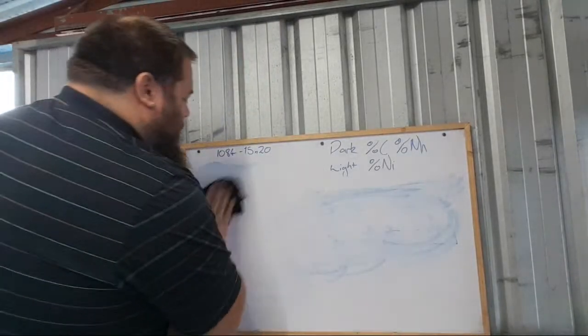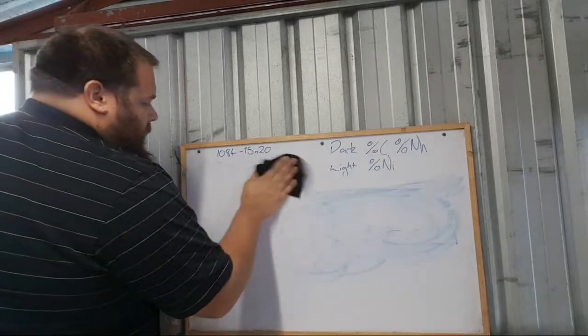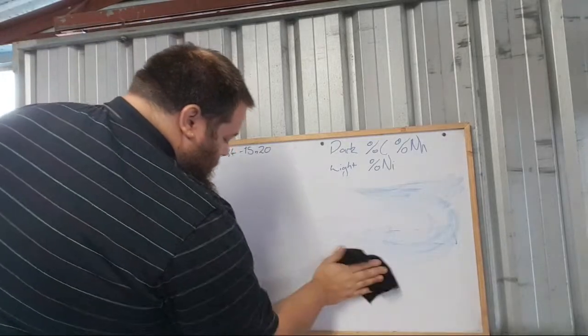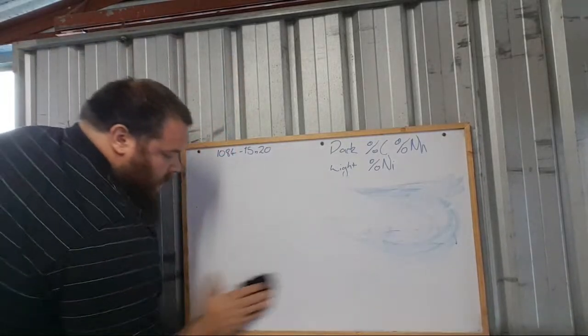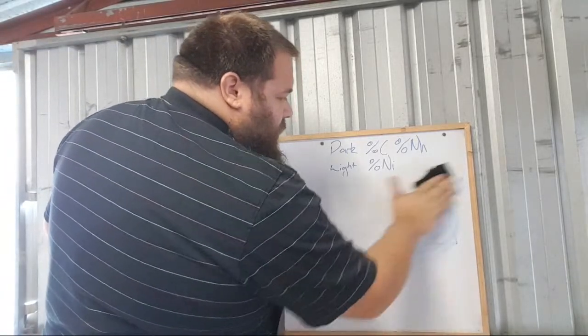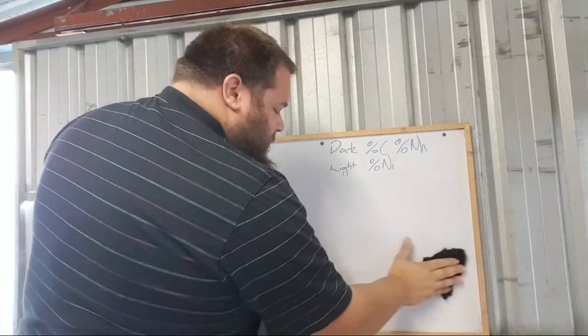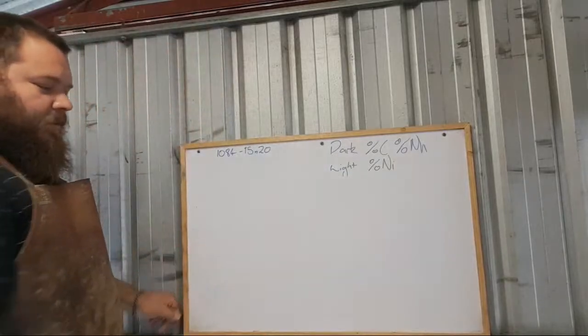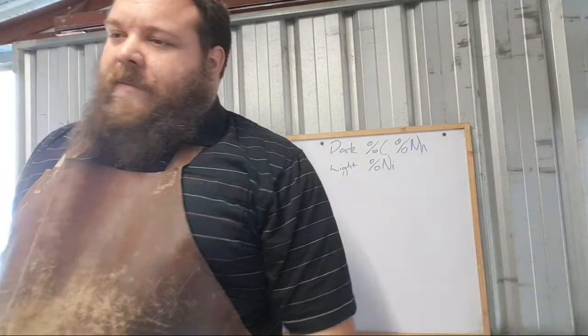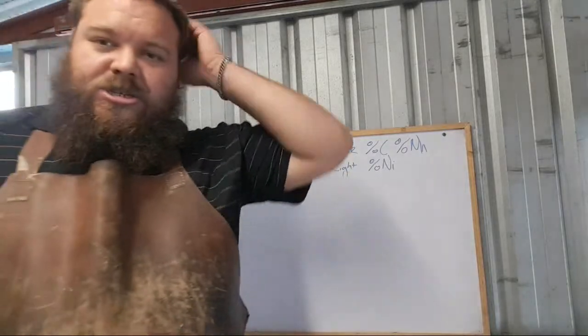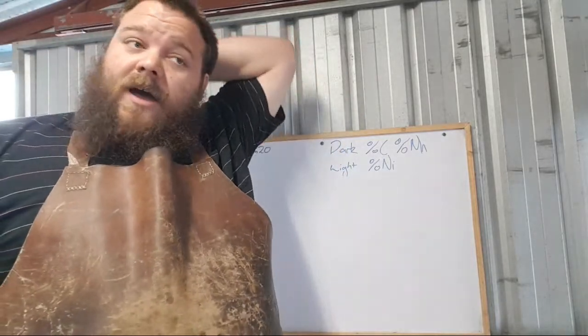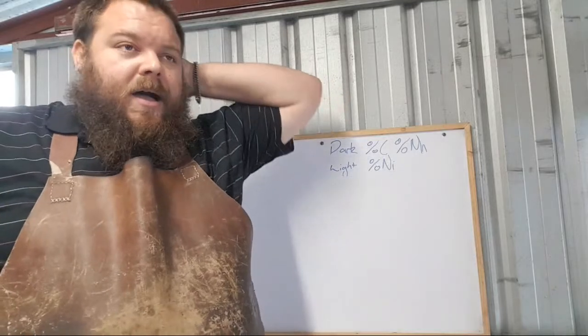Yeah, and from crushed W's, you can make a lot of different patterns. Now, someone asked me if leaf spring and file steel would make a decent pattern. While leaf spring and file steel do etch differently, what they don't do very well is weld. 5160, as a general rule, absolutely hates to weld in Damascus. It's something to do with the amount of chromium and silicon in it. It just hates welding. I can't get it to weld most of the time.